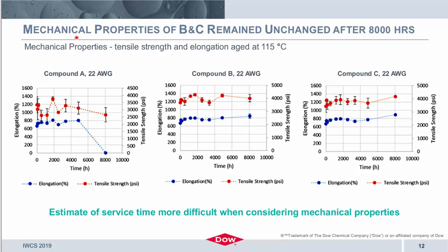Now I'll shift gears and talk a little bit more about the mechanical properties. Here we're focusing on tensile and elongation. In the plots shown here, we're looking at the aged elongation and tensile strength for the given 115 degree C samples. I'm showing these representative samples because actually at the lower aging temperatures, the properties remained relatively unchanged out to 8,000 hours. So a very long aging time, and the material properties remained unchanged at the lower temperatures.